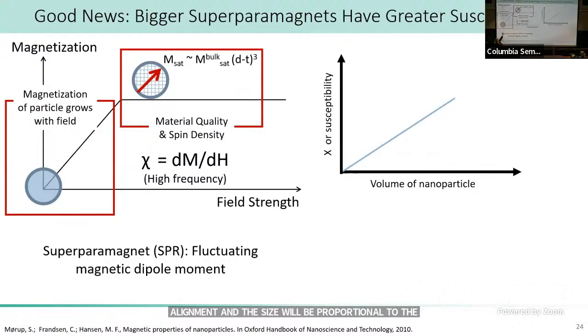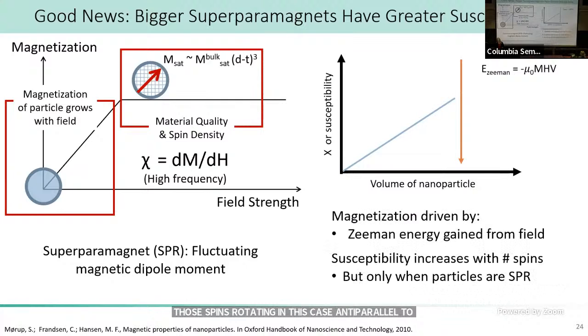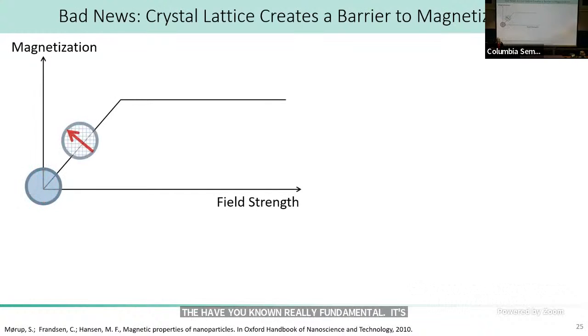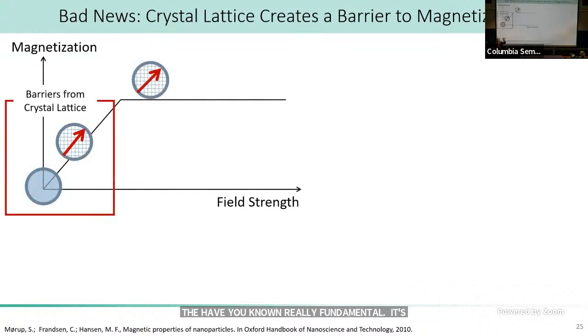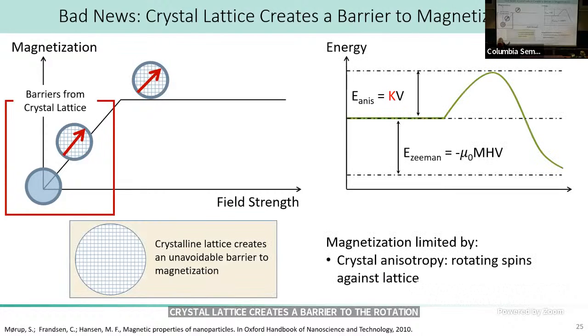The problem is, why don't they magnetize fully at very, very small fields? What's the barrier to those spins rotating, in this case, anti-parallel to the applied field? And the reason is really fundamental. It's that our systems have a crystal lattice, and that crystal lattice creates a barrier to the rotation of the spins. And as a result, their susceptibilities are very, very small. It's hard to make them magnetized because those spins are working against basically the crystallographic lattice itself.